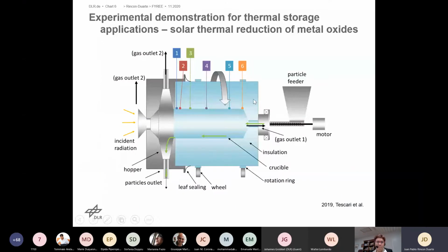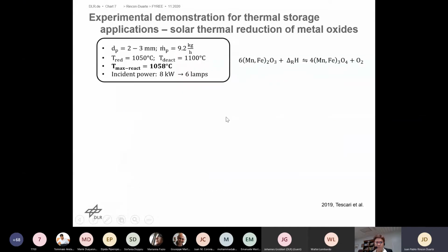If we have a look at the inner side of the reactor, we can observe the crucible in more detail. This blue part is insulation material that we put in order to avoid thermal losses. And we also put several thermocouples along the axial direction of the crucible to have the temperature profile of our reactor. In our experimental campaign with this iron manganese oxide, we had a material whose particle size was between 2 and 3 millimeters.